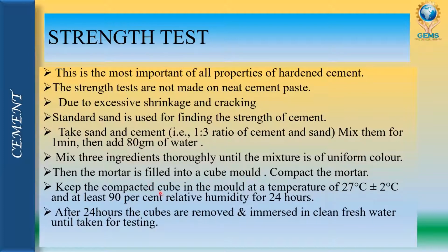After compacting the mortar, it should be kept at a temperature of 27 degrees Celsius plus or minus 2 degrees Celsius and at least 90% relative humidity should be maintained for 24 hours. After 24 hours, the cube should be removed and immersed in fresh water until the test is conducted. This is the procedure for making a mold for the strength test.